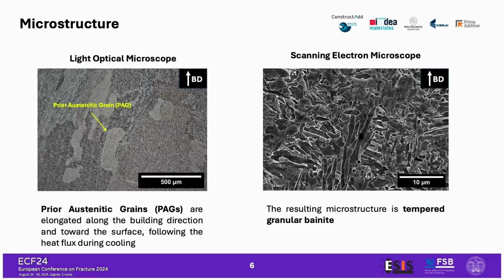Let's start with a quick overview of the microstructure. The as-built microstructure is basically tempered granular bainite, and this is the microstructure that we observed all along the deposited wall. And under the light optical microscope, we observed prior austenitic grains elongated towards the surface and along the building direction, following the cooling heat flow.